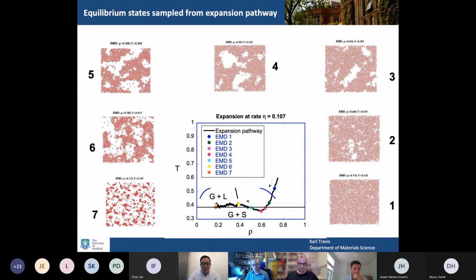Quantitatively, the way you would do this, and the way I did it back then, is by counting clusters and performing some cluster statistics. These are Stillinger clusters, and then you can show that the mean fragment size is quite different, the fragment distribution is quite different along these two different pathways.